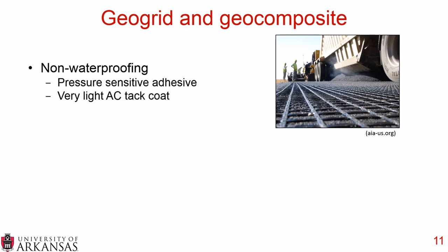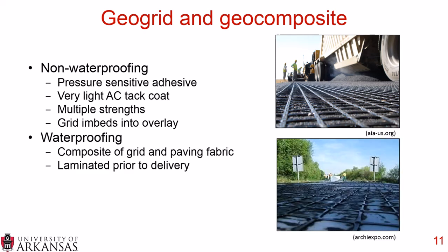Now, moving to geogrids and geocomposites, these are no longer a fabric. This is more of a grid type material. These are non-waterproofing, and that is because they just use a pressure-sensitive adhesive and a very light asphalt cement tack coat. You can have multiple strengths of geogrids and geocomposites, and the grid embeds into the overlay. So you can see in this picture, you're placing hot mix asphalt on top of the geogrid, and that hot mix asphalt will go down into those cells and embed itself into the geogrid. So those are all non-waterproofing options.